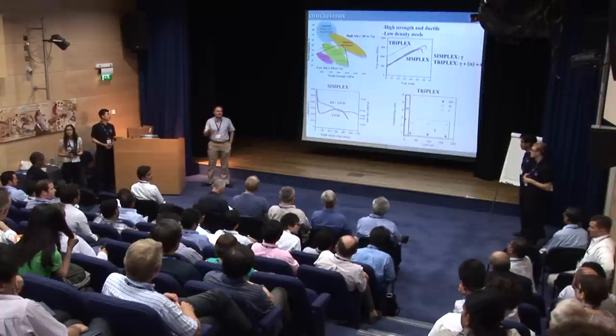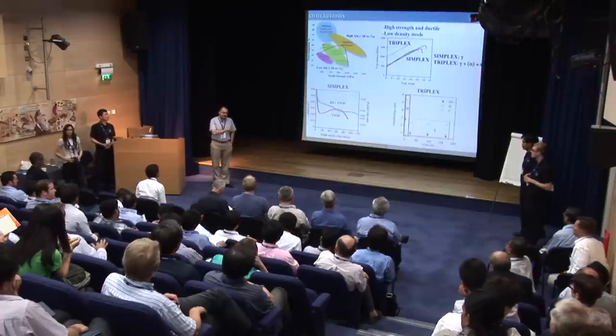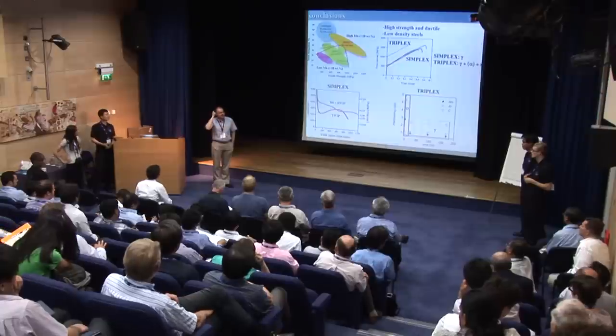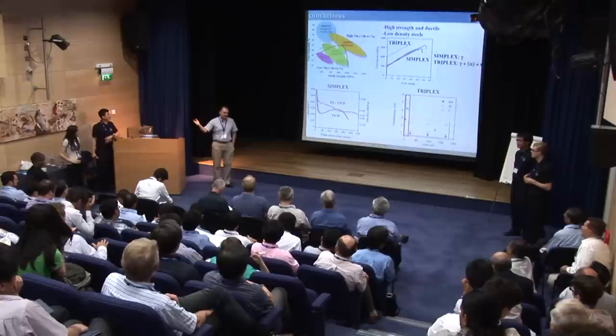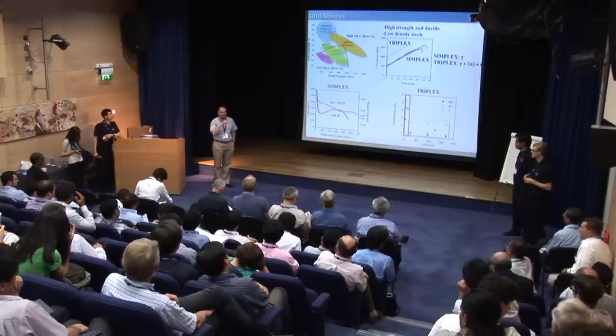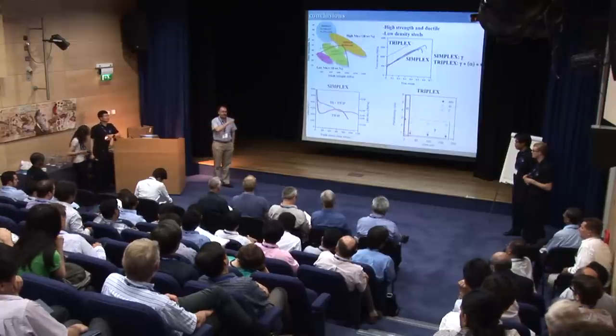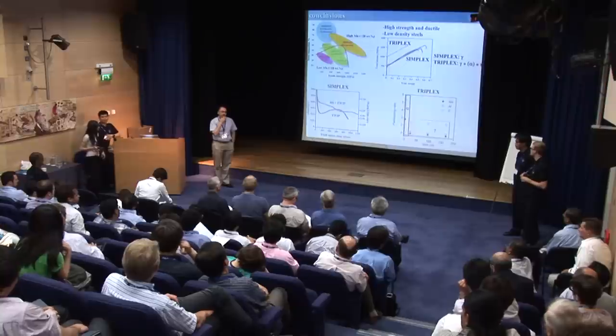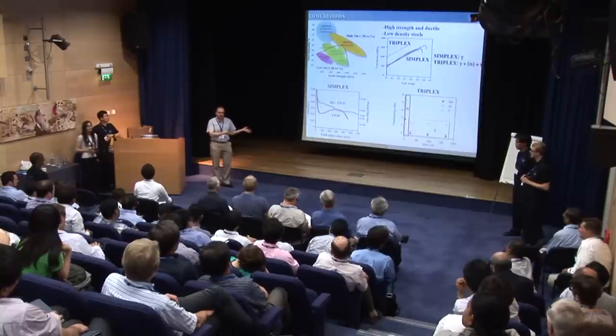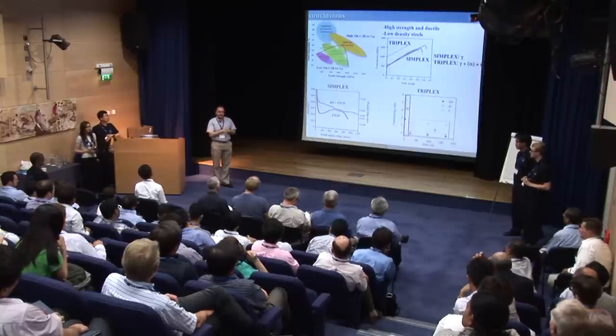So if I go to the austenite and come back, let's say there. Sure. I mean, thermal stability is relative. What I was just mentioning is that thermal stability is relative to another system. It's surprising that after 2 weeks at 600 degrees, we still retain nanocarbide particles. This is an indication that these alloys can exhibit good mechanical properties at higher temperatures. This is mainly my idea, my explanation.